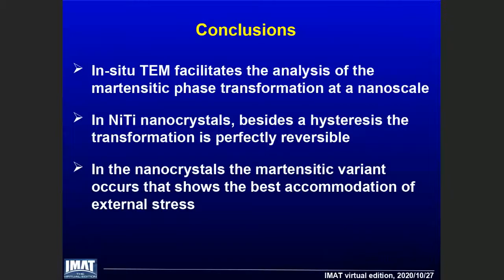In conclusion: using in-situ TEM facilitates the analysis of martensitic phase transformations at the nanoscale and specifically in nanoscale volumes. In the nickel titanium nanocrystals, besides the hysteresis, the transformation is observed to be perfectly reversible. And in the nanocrystals, the martensitic variant that occurs is the one showing the best accommodation of the external stress. Thank you for your attention, and I would be happy to take some questions.